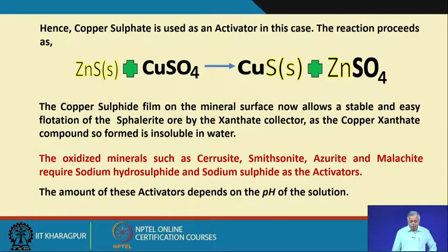Now, what is happening now? This ZnS plus CuSO4 gives you CuS, a copper sulphide film, on the mineral surface. Now, this allows you a stable and easy flotation of the sphalerite ore.